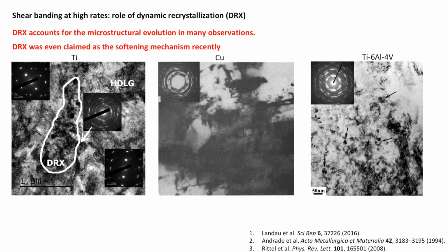Researchers from different groups have also carried out TEM investigations to look at the microstructure of shear bands. Here are some examples from the literature: titanium, copper, and Ti-64. Looking at the first example, titanium, in the region outside the shear bands, you can see single crystals depicted by the sharp spots in the diffraction pattern. For the grains within the shear band, the crystals have turned nanocrystalline, giving you the ring pattern. In the shear band community, the formation of those nanocrystalline grains is attributed to the heat and the localized deformation leading to dynamic recrystallization.